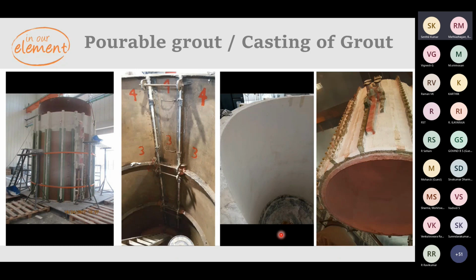So here I'm talking about, I'm not sure how many people here would have known about these types of grouting systems. Normally, the grout is done by troweling application, but we have grouts which can be pourable or cast. So this is a pourable grout, or it can be called casting of grout. Here, as you see in the slide, we set the form as per the lining thickness or grout thickness suggested by the OEM, and we use a self-flowing castable for doing this operation. We also introduce a small vibration to the form.